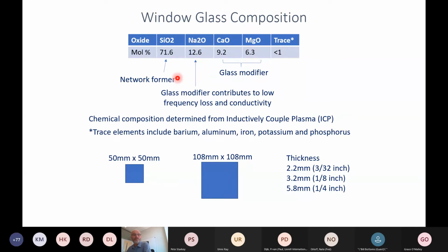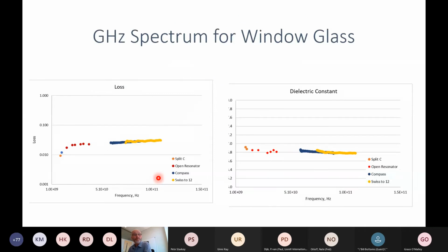We tested these over a wide variety of frequencies here. This shows some of the geometries we used for the measurements. And this is a little bit small, sorry about that, but this shows a loss over here going from 1 gigahertz all the way up to 100 gigahertz. And you can see here it's fairly flat, somewhere between 0.01 and 0.1. So the loss is fairly high for window glass. And here's the permittivity value, a little cut off there, but it's about 6.8. As we look at all these different techniques, they align very well through this broad frequency range. So that's window glass.